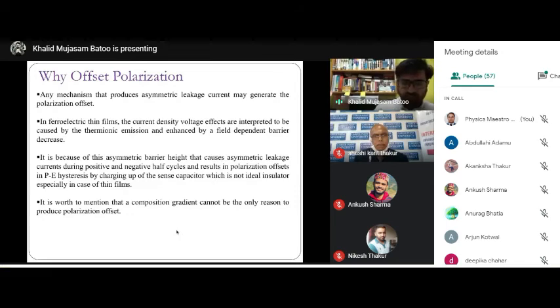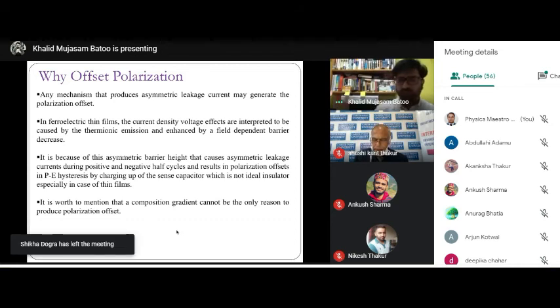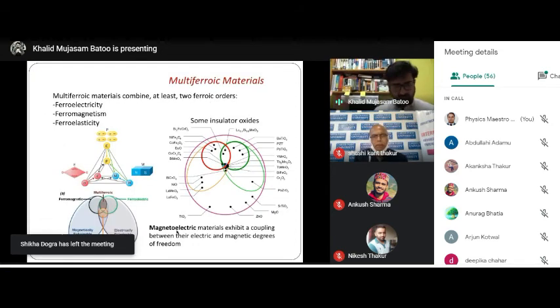This shows that our material can be a good application for FRAM at high temperature. At high temperature, the temperature effect acts as a depolarizing or distorting element that cancels the polarization effects. However, this material was self-reliant and good, showing that the properties are better to a certain extent.